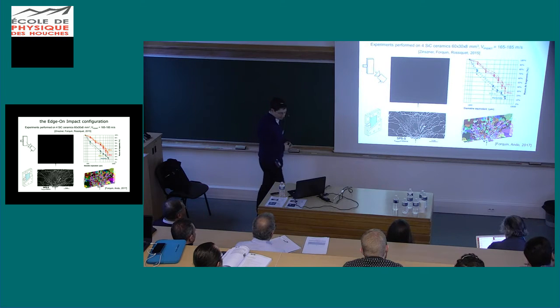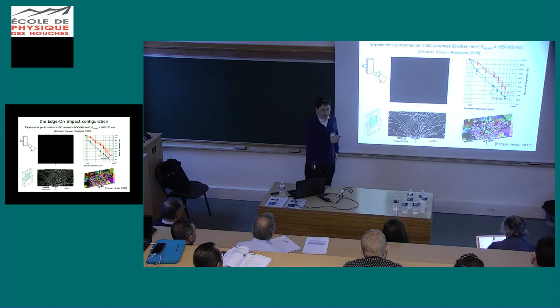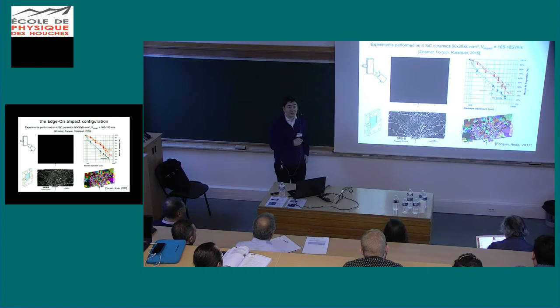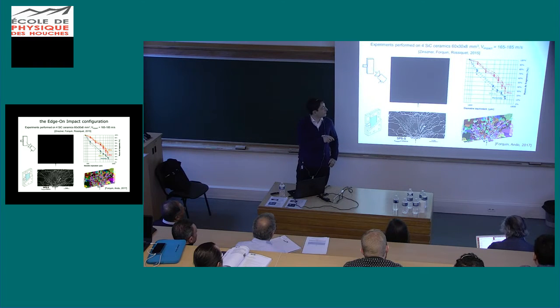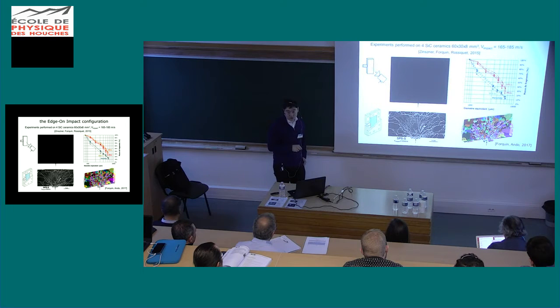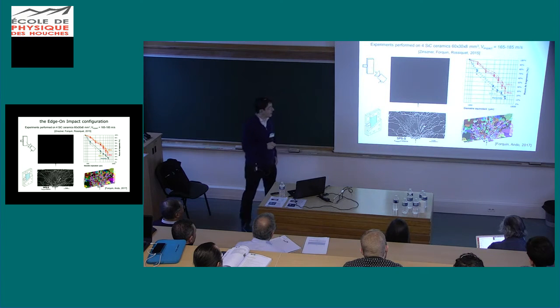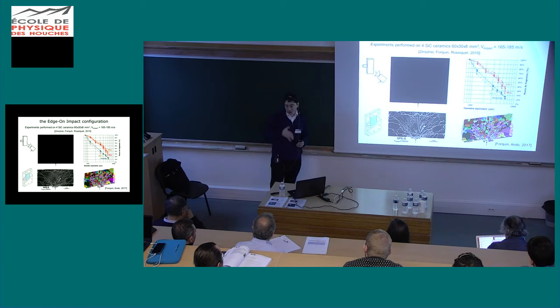And what is important is to observe that, first, the fragmentation process is a deterministic process. That is, you can see two samples of the same ceramic grade will lead to the same fragment size distribution. It's, I think, very clear here. But when you compare different ceramic grades, you can observe different fragment size distributions. So there is a strong influence of ceramic microstructure on the fragmentation process and fragment size distribution.